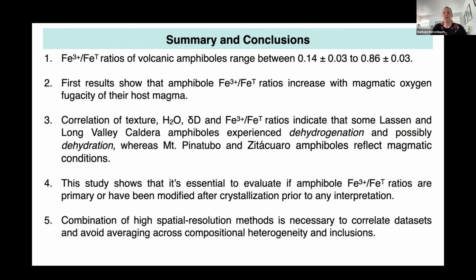Okay, so providing you with some summary and conclusions. So by using synchrotron mass spectroscopy and combining different setups, we're able to determine Fe3+/FeT ratios in volcanic amphiboles, which range between 0.14 and 0.86, so relatively wide range. And as a first result, we showed that amphibole Fe3+/FeT ratio increased with the magmatic oxygen fugacity of the host magmas.